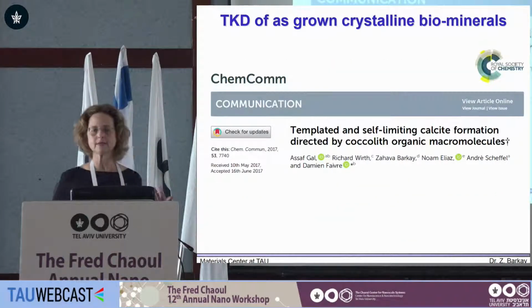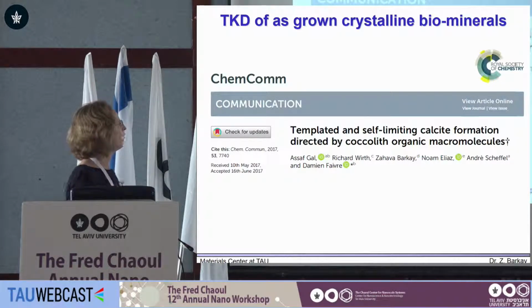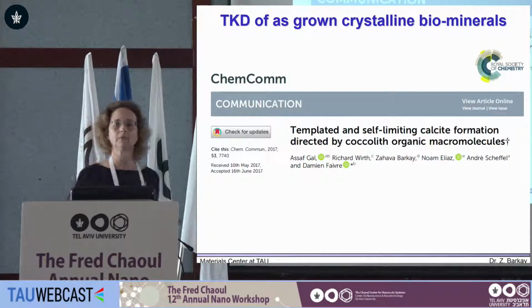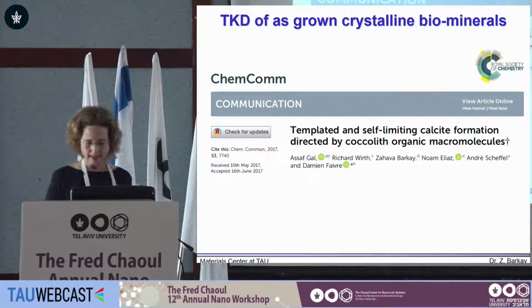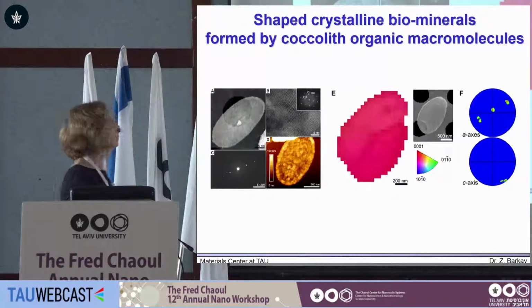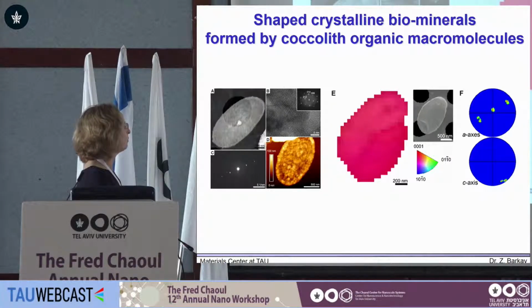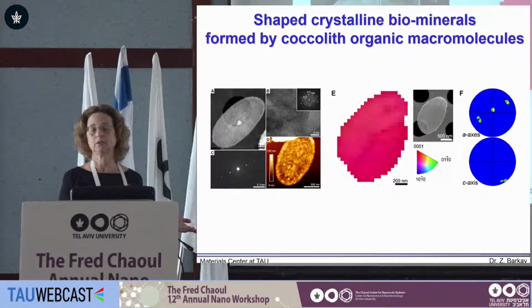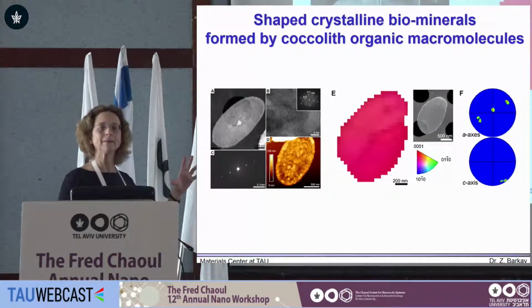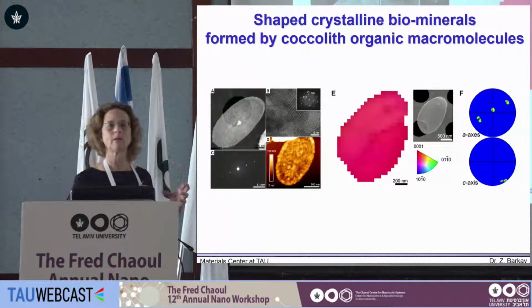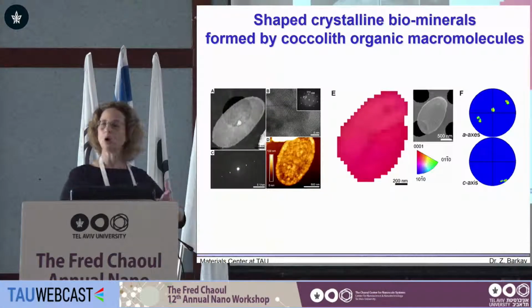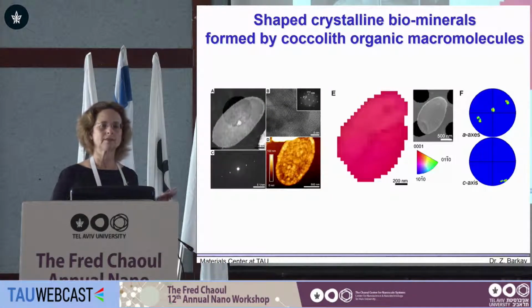So the first is the as-grown. These are biominerals, actually calcite, that were obtained with coccolith organic macromolecules, and this was done by Asaf Gal from the Weizmann Institute, who brought the sample. Asaf already had information from TEM about crystallography and AFM information, but what was missing was orientation from the whole feature of the 1 micron size biomineral. What he was asking was to know the real orientation of this hexagonal structure.